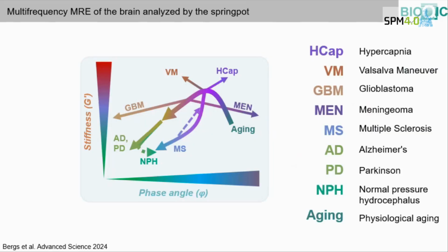This looks funnily colorful, but there are tons of data behind, which show in the human brain how stiffness and phase angle, so elasticity and fluidity, change over different processes and disease. For example, with aging, we see an increase in stiffness and a decrease in the fluidity, while most brain diseases are associated with softening. So it gets always softer, and the fluidity is also decreasing in most cases, which we have investigated so far. So Alzheimer's disease, Parkinson's disease, normal pressure hydrocephalus, and in some disease like multiple sclerosis,